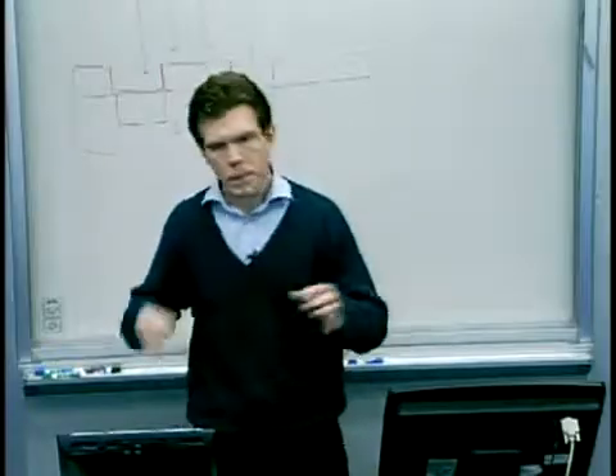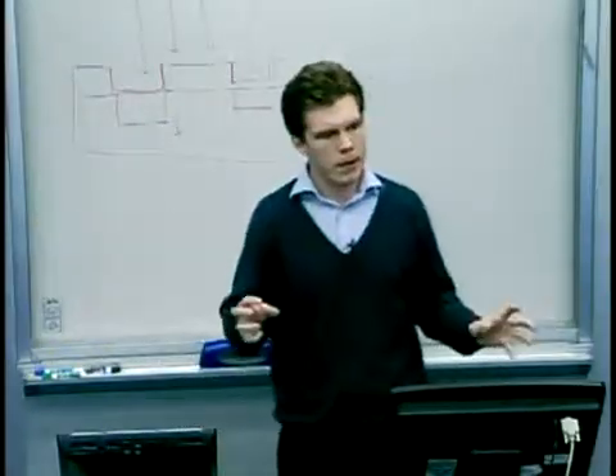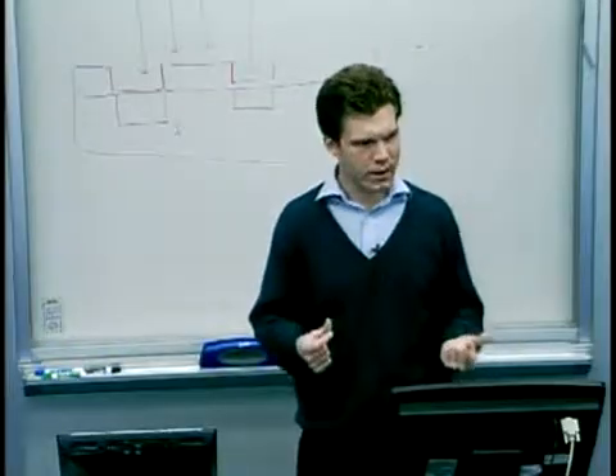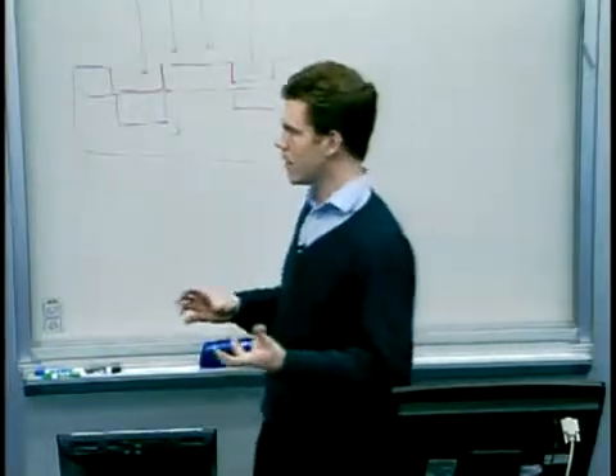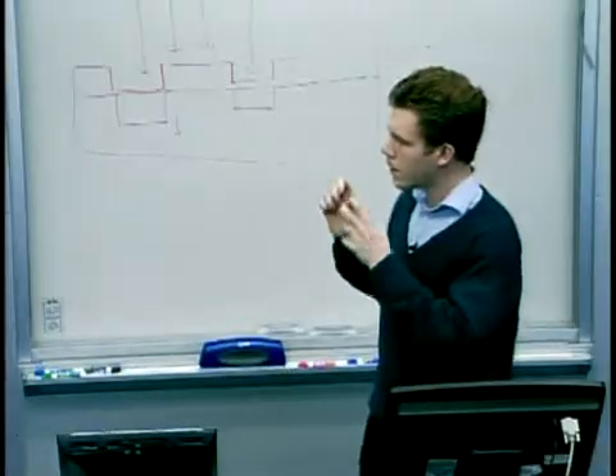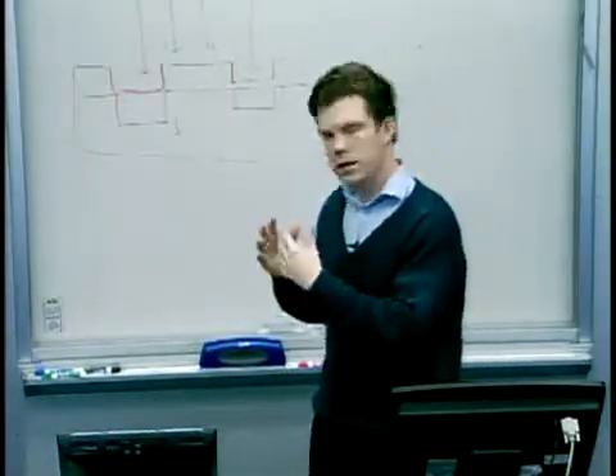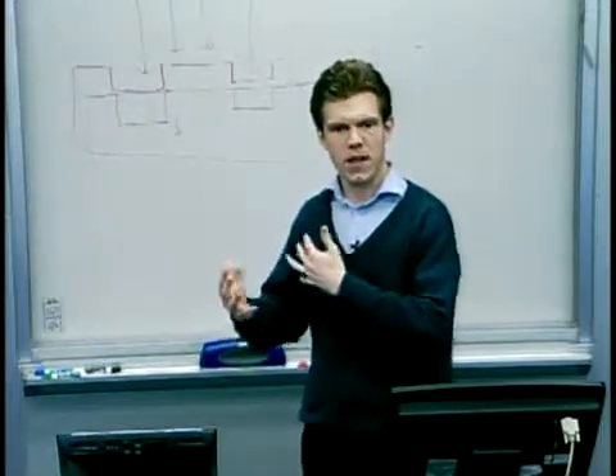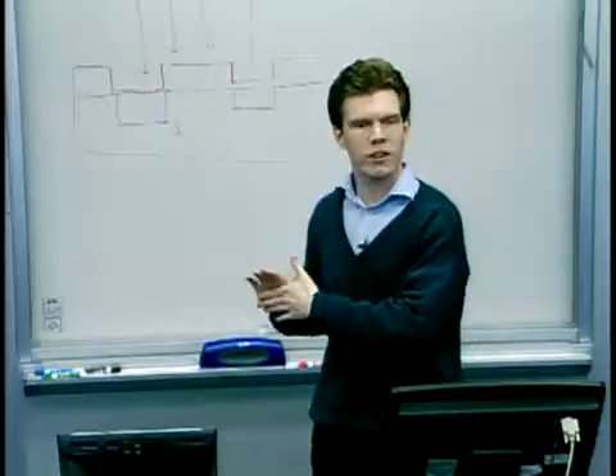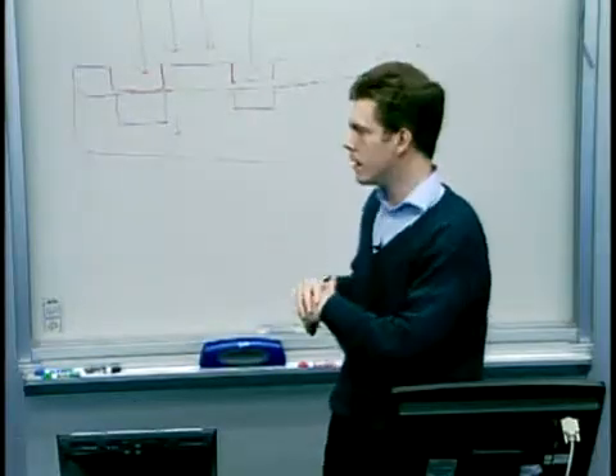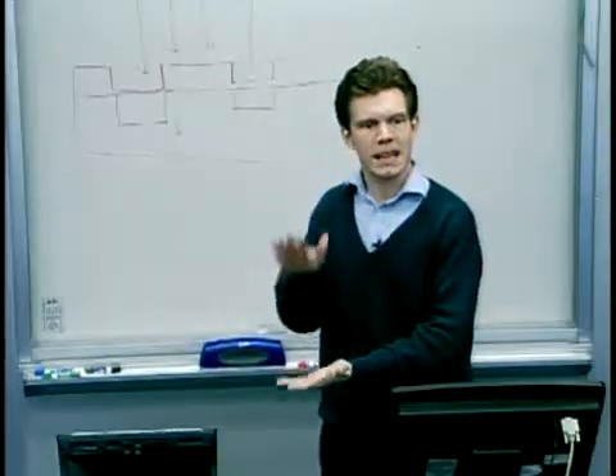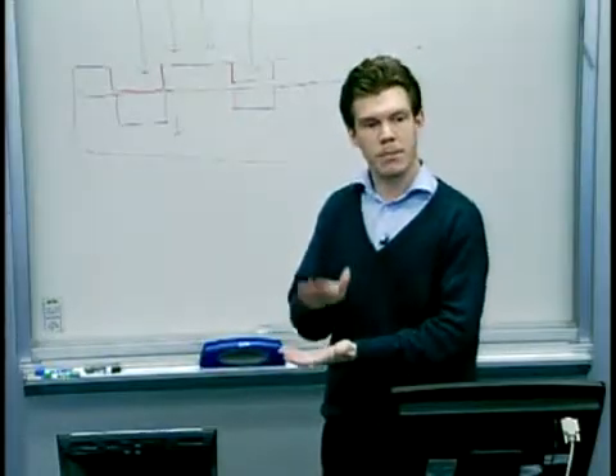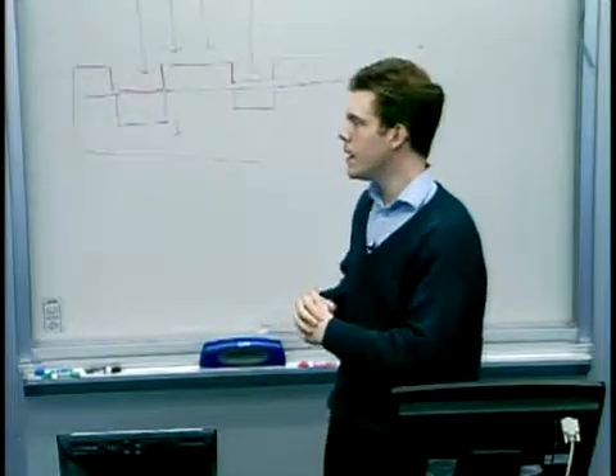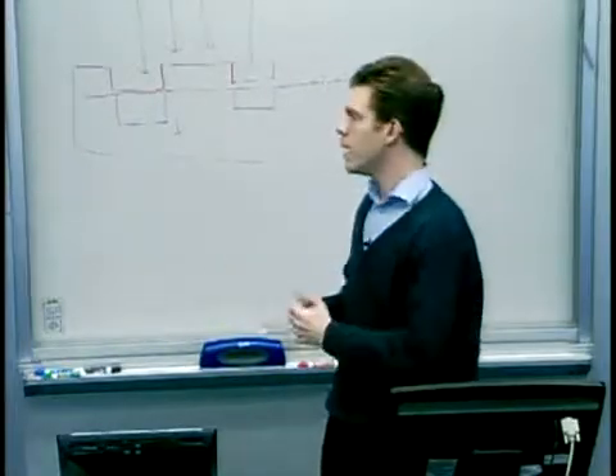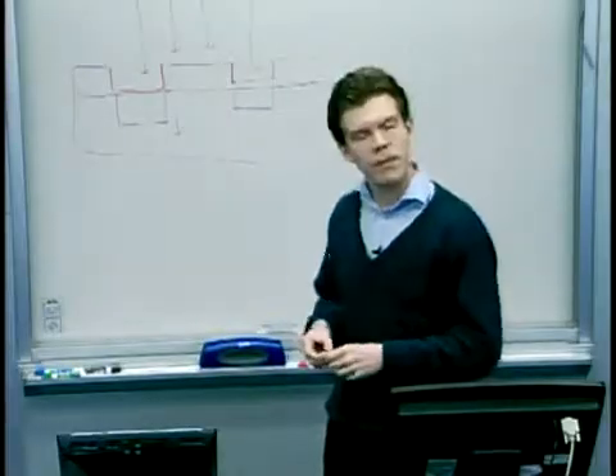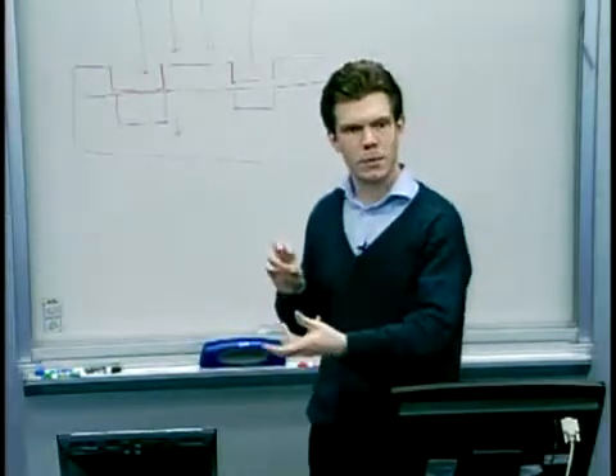Now I'm just going to split the problem up into three notional length scales so that we can have a clearer picture of what's going on. And at the largest length scale, you can think of variations in the quality of the embossed features from one side of the substrate to the other. And that might occur because the two heated plates that are compressing the stamp and the substrate are not perfectly parallel, so the pressure's greater on one side. It might be because one of the plates is bowed or wavy, or it might be to do with simply the mechanics of the substrate itself.